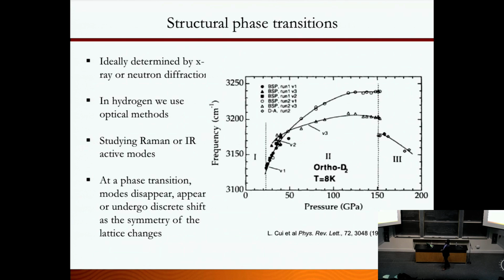So how do you determine a phase transition in materials like hydrogen? What you're seeing in this graph is pressure versus frequency, the IR and Raman vibron frequency of the hydrogen molecule, the stretching mode. You track that under pressure. When a material goes through a phase transition, you will see peaks disappearing or new peaks appearing. When the symmetry changes, you will see either a discontinuity, or modes disappearing or new modes appearing. If you look here, the vibrons we have right here all disappear, and then a new vibron appears here, with a huge difference in frequency. It's a clear indication of a phase transition. This is how we identify new phases in materials like hydrogen, where it's difficult to do X-ray.